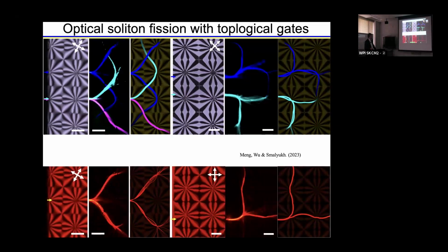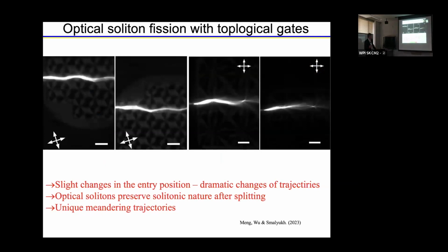These splittings can happen multiple times. So you can have daughter, granddaughter type of solitons. But a very simple way to understand this is that the solitonic beam of light is incoming, and when it crosses such a vortex line, you can see in here, part of it will be deflected in one direction, part in the other direction. And then if power is sufficient, these solitons will remain as optical solitons. You remember, you need to have some threshold power to distort the optical axis in order to create nonlinearity sufficient for their existence. On the other hand, if the power is not sufficient, then they will decay, intensity will decay, and then it will be scattered out, right?